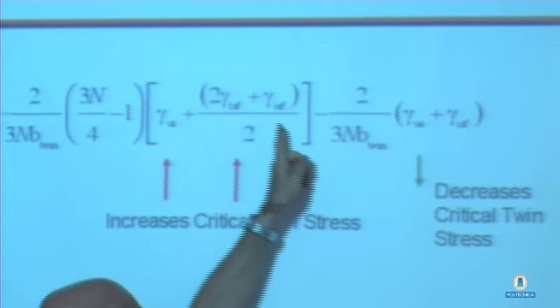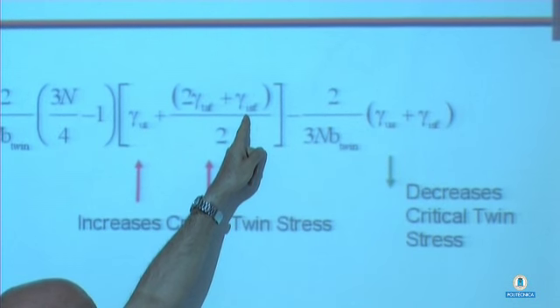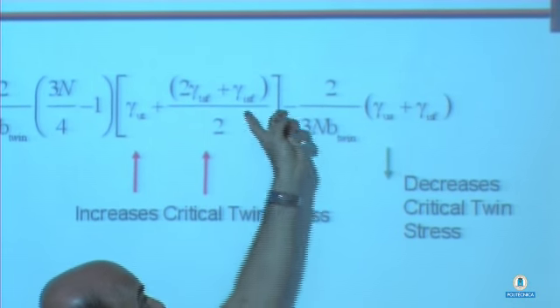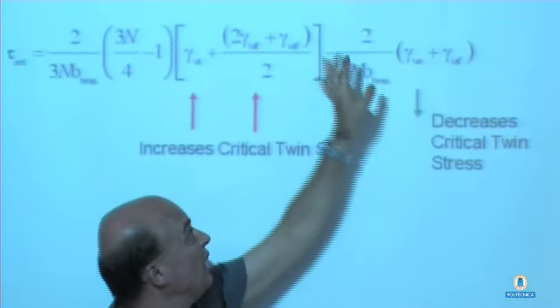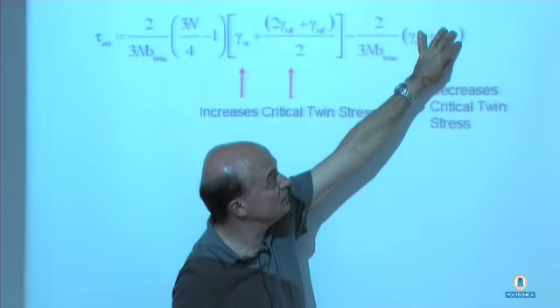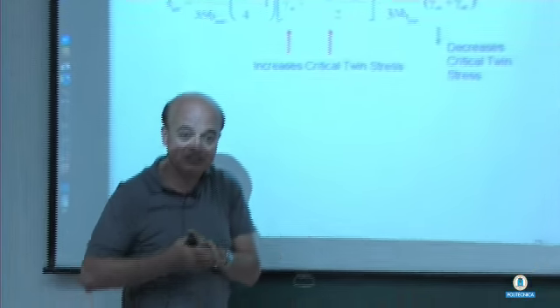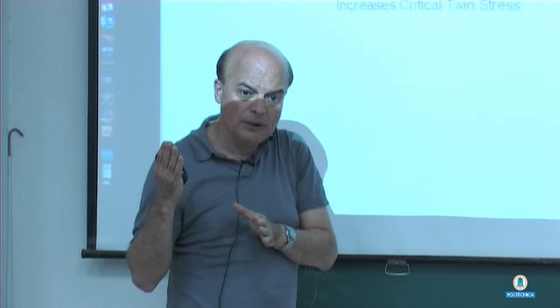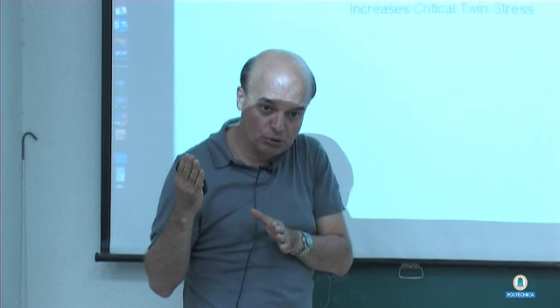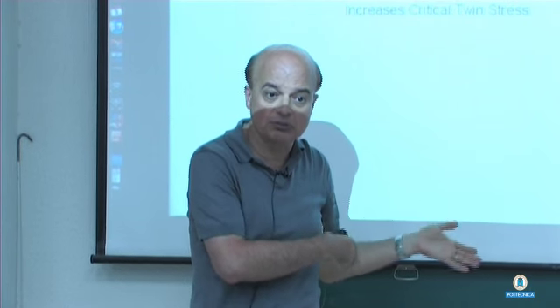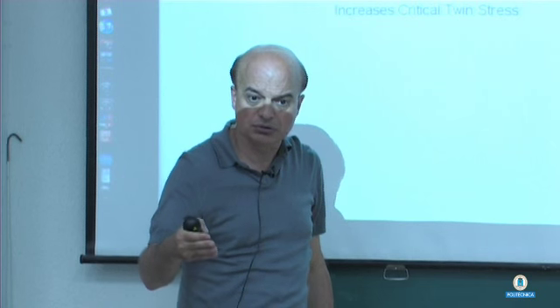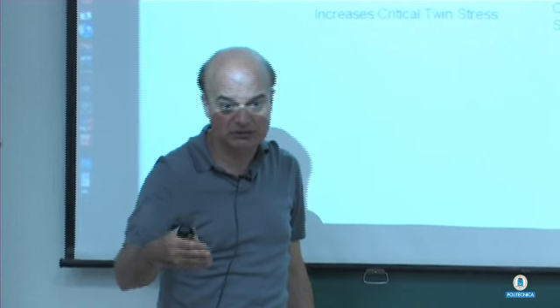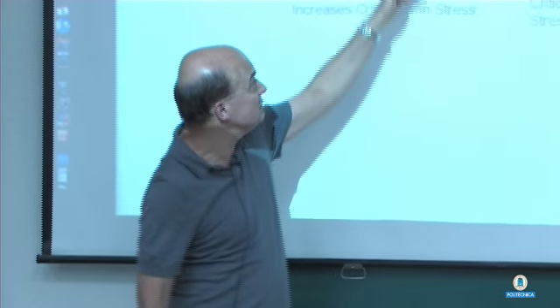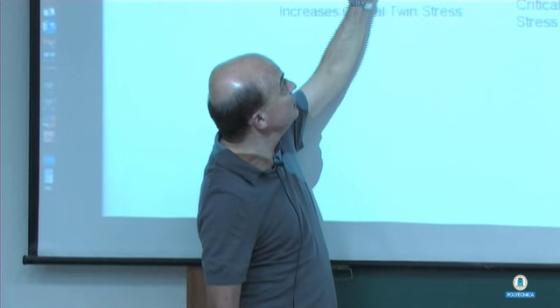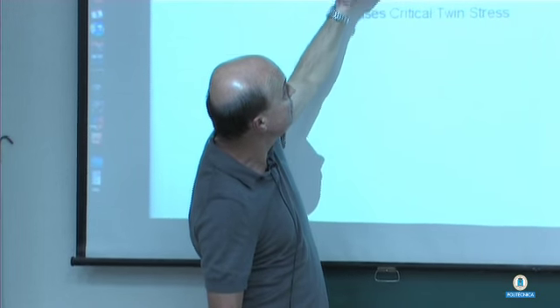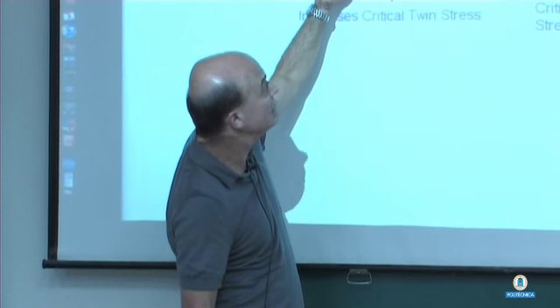Now, ISF is appearing here, and ISF is appearing there. Actually, this term dominates this term. The ISF here is larger than that. So if you increase the intrinsic stacking fault, the twinning stress will also go up. And that's consistent with the Venables model and what we teach our students in the undergraduate classes and graduate classes. But that has a modifying effect. This is a dominating term, actually, it turns out.